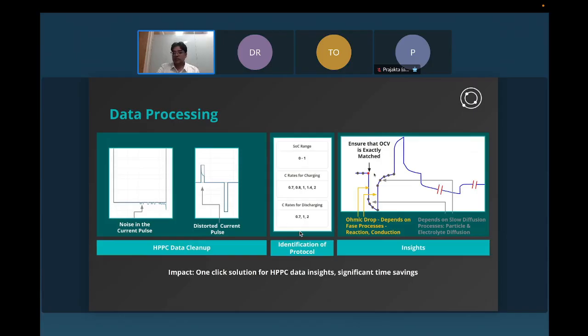When I say pulse regions, you have the rest period after which you start a pulse, and then you will see that there is a sudden ohmic drop in the voltage, and then you have a slower decay, which is the relaxation part of it, predominantly driven by the diffusion process, whereas the initial drop that you see over here is a combination of the internal resistance as well as the overpotential, which is dependent on the reaction rate.